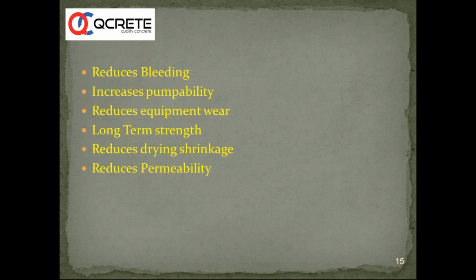The advantages to the customer when buying fly ash concrete are that long-term strengths are increased, with reduced drying shrinkage and reduced permeability. As a result of secondary hydration, you have a more stable, denser microstructure, and you are also reducing the water cement ratio in the body of concrete when you are using fly ash, and hence the permeability is reduced significantly.